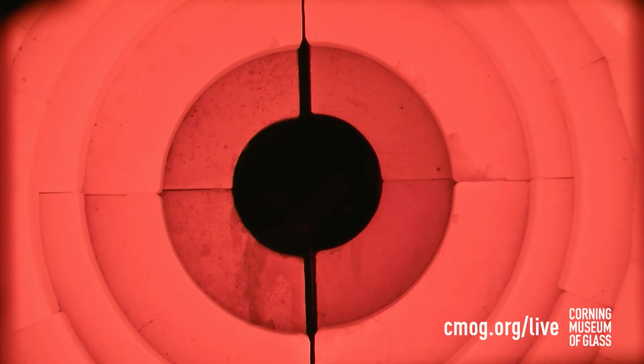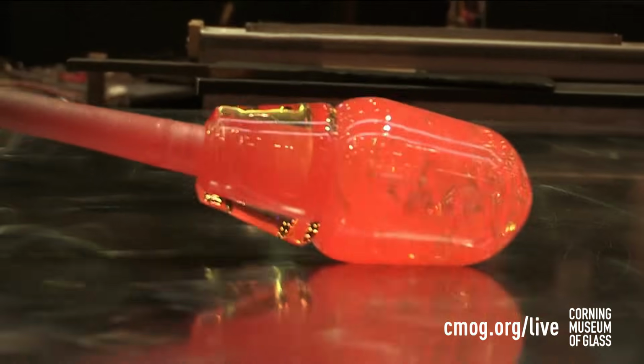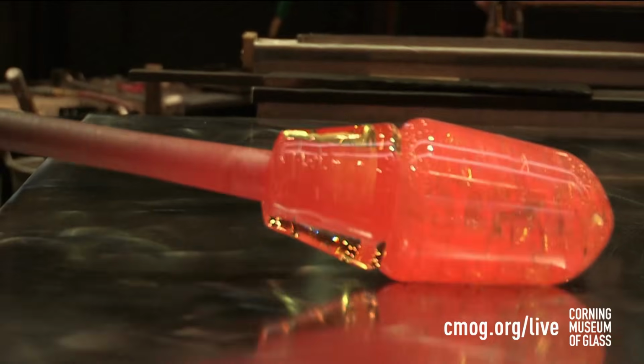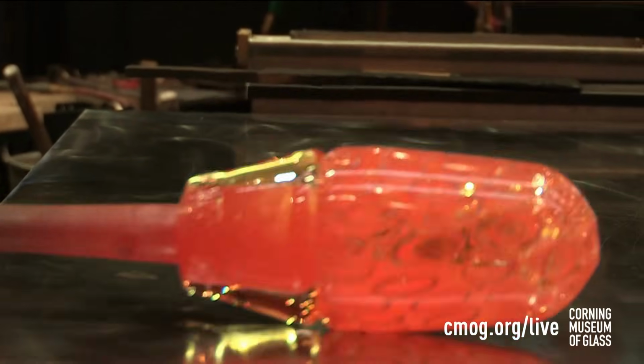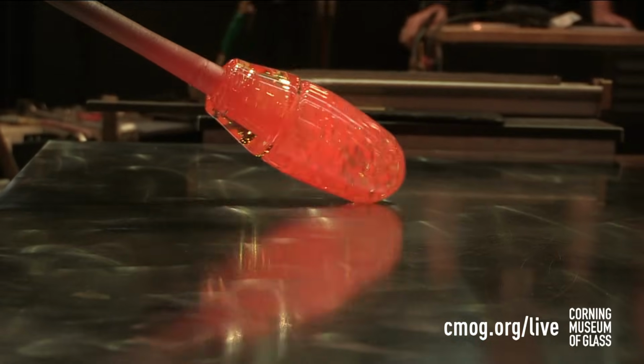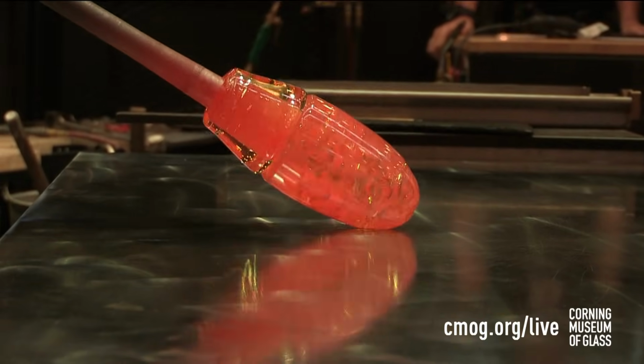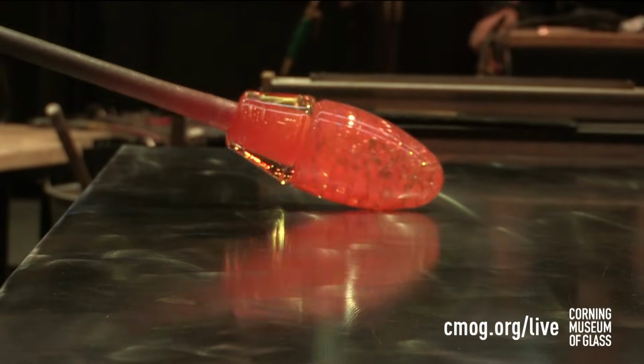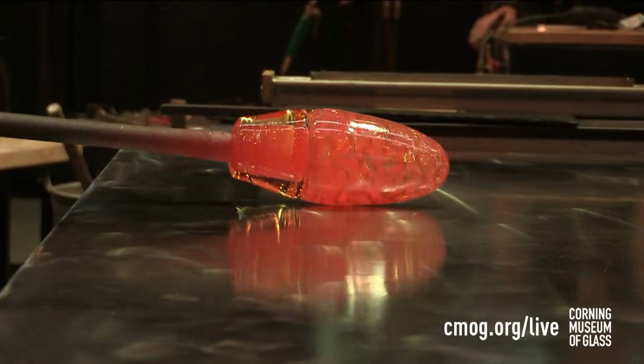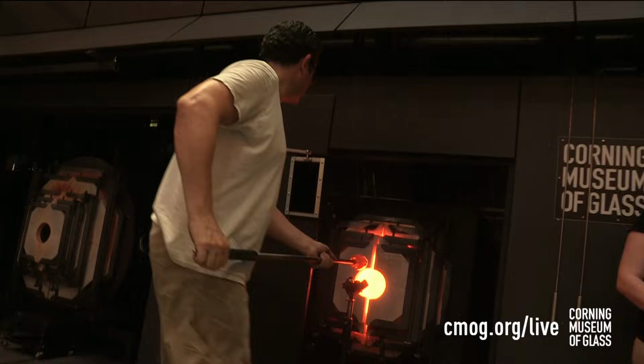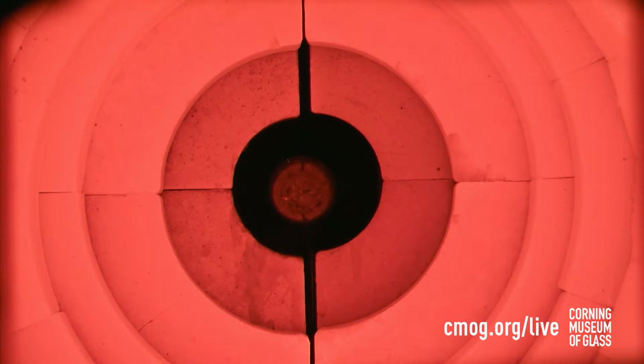Also, we soak them in water. Now, this is just regular Corning tap water. It's not heated, it's not cooled down, but that water will turn to steam the instant it touches that hot glass. Keep in mind, it's around 2,000 degrees. So that steam actually separates the glass from the tools that we're working with. That's the important part. So as we use these wet tools, you'll notice we dip them back in water. We continue to add water to them. When the water turns to steam, that's actually called the Leidenfrost effect. If you've ever been cooking in a pan and you drop some water or oil in there and you see those little beads dance around, that's the same effect, same thing.